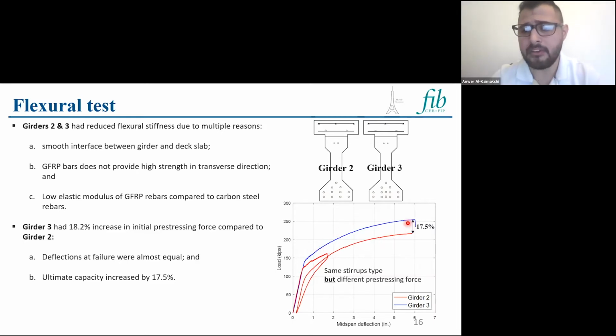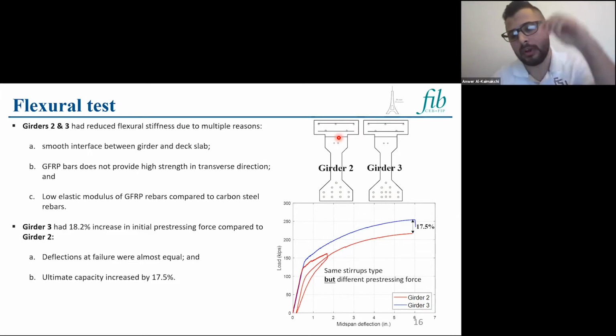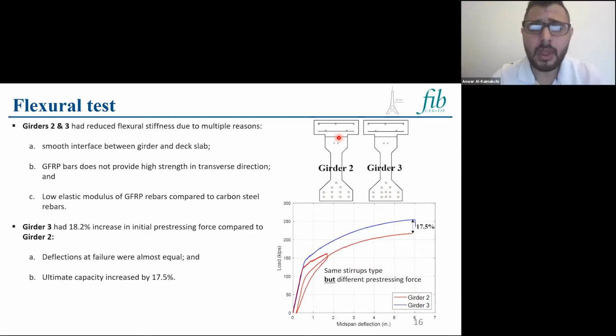And then the main reason for that was because the interface region between the girder and the deck slab was smooth, so we didn't roughen it during fabrication. And also GFRP rebars do not provide high strength in their transverse direction compared to their vertical direction. And also because of the low elastic modulus of the GFRP rebars compared to the carbon steel or stainless steel rebars.